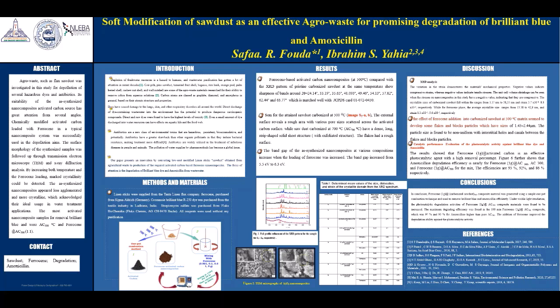Conclusion. In conclusion, ferrocene with 1 gram with carbonized sawdust, which carbonized at 500 centigrade composite material was generated using a simple one-pot technique and used to remove brilliant and amoxicillin. The most efficient one is ferrocene with 1 gram and activated carbon composite, which is carbonized at 500, were found to be increased, and the activity arrived to 97 and 93 for amoxicillin and brilliant blue respectively. Thank you.